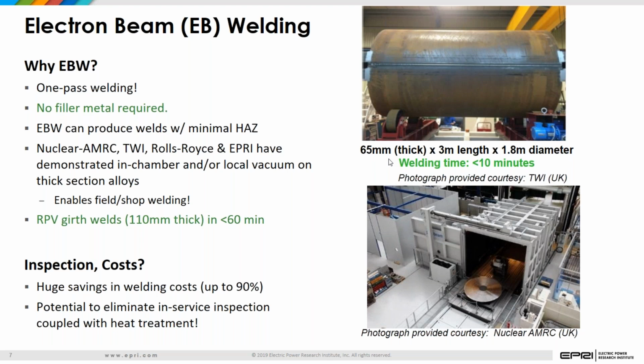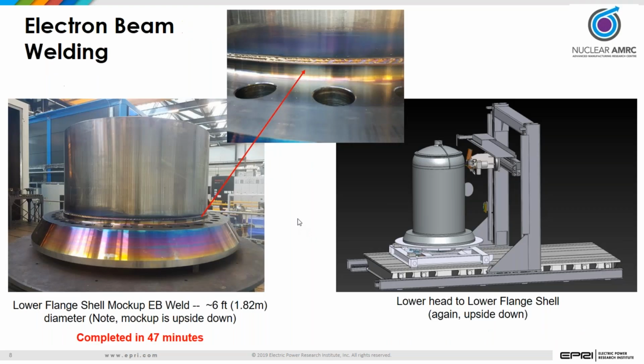If you look at the bottom screen, this is a large vacuum chamber that's used for electron beam welding. In fact, this is what we're working with Nuclear AMRC on today, wherein we're assembling portions of the upper and lower assembly of the two-thirds scale reactor. I do also want to point out one other area we're looking at: in addition to the overall savings around electron beam welding, we also believe there's a potential to eliminate some of the inspection issues around this, and I'll touch on that a bit in the codes discussion shortly.